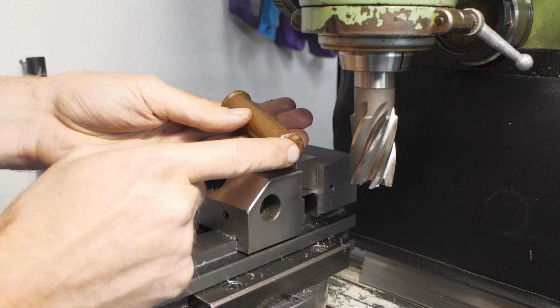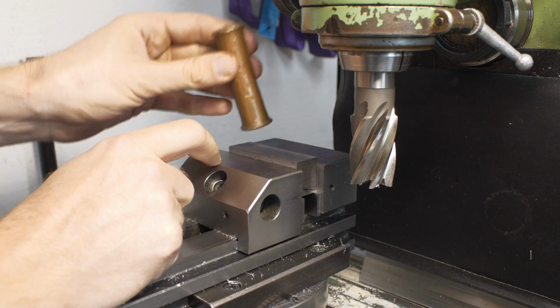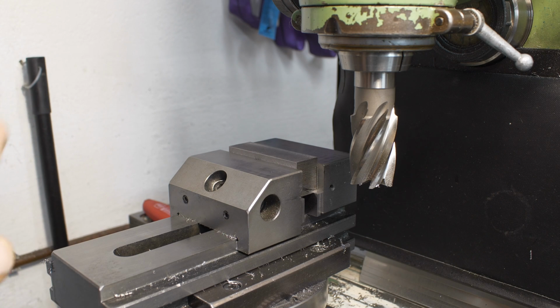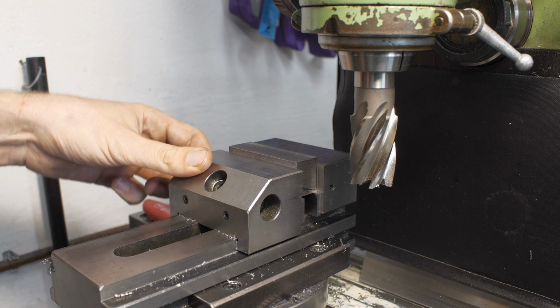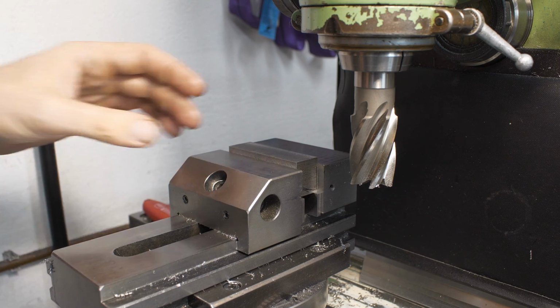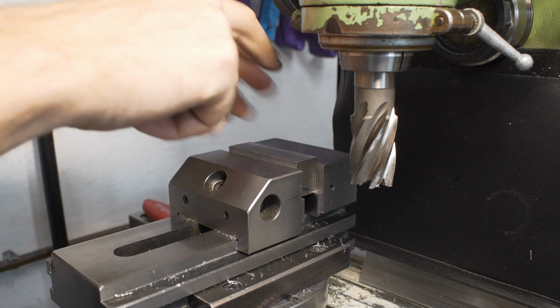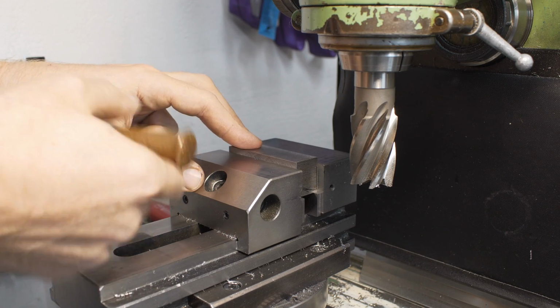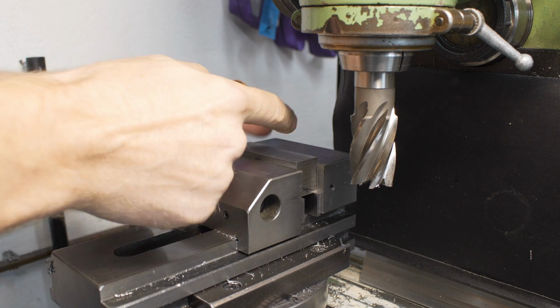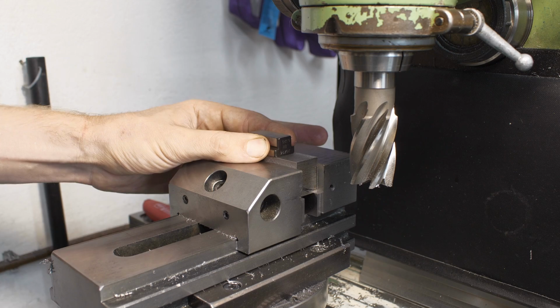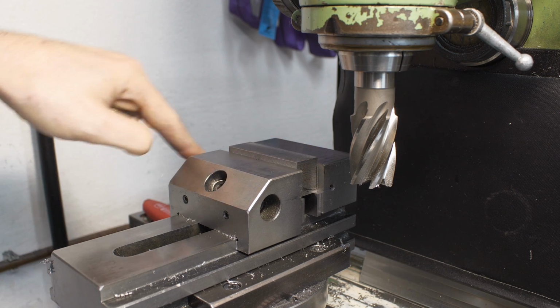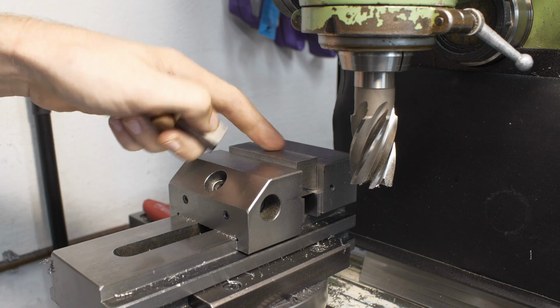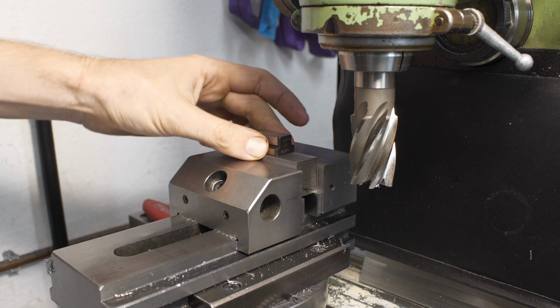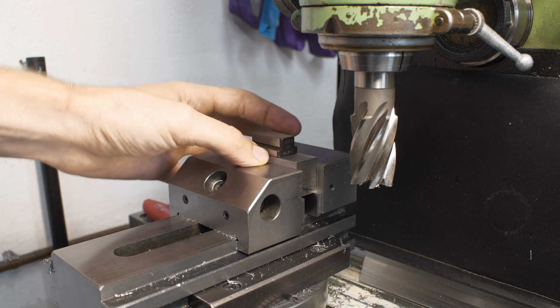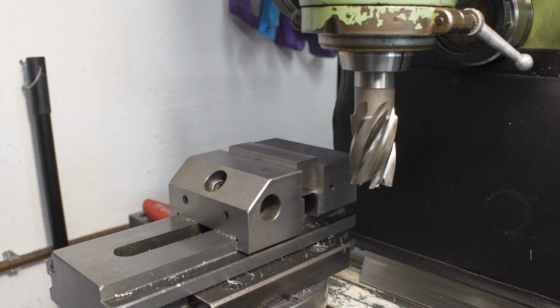Also, despite copper being soft, it can mar parts, even steel parts. You can leave marks if you're a very dedicated hammerer of items. So be careful there. Robin has an interesting technique for seating parts. He's using a small hardened and ground block that he puts on the part he wants to hammer, and then uses, I think he has a brass drift and hits the ground block. It would look like this for Robin. He has a ground block here, and then doing this. That way he does absolutely not get any marring on his parts if the surface of the in-between part is clean and surface ground and doesn't have any burrs or chips on it. About a million things to consider when you square up stock.